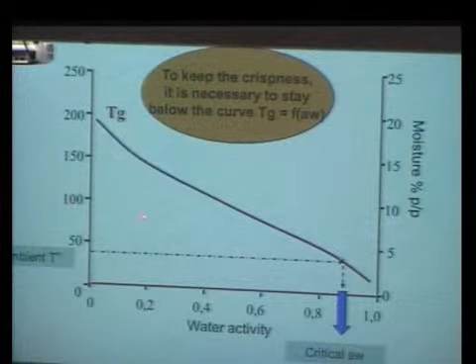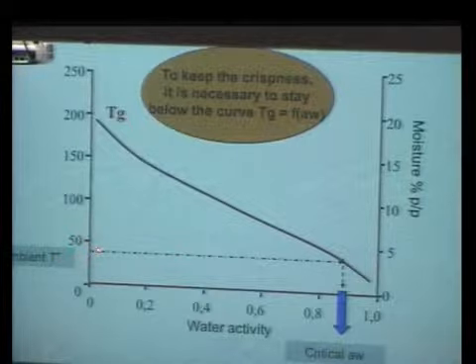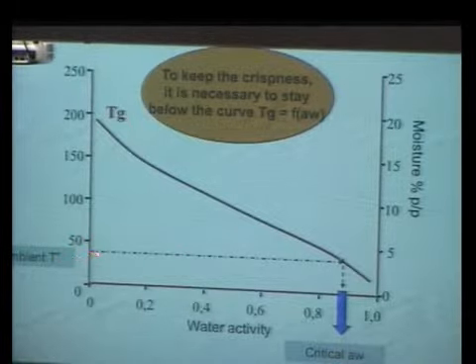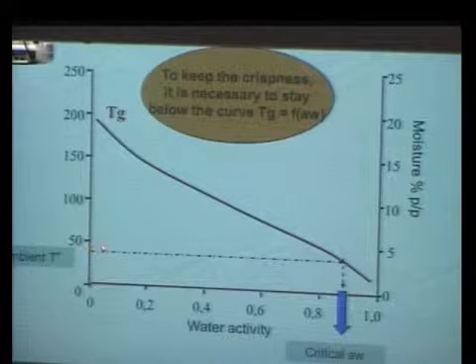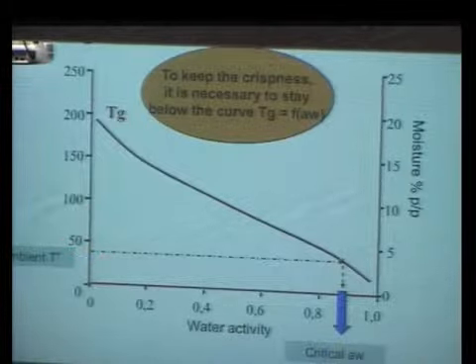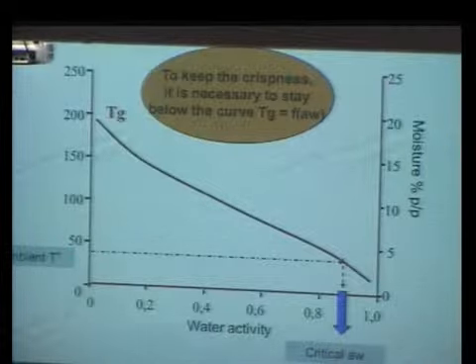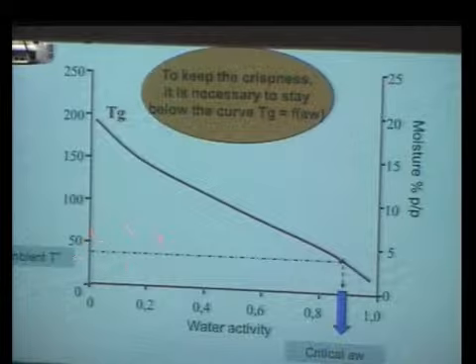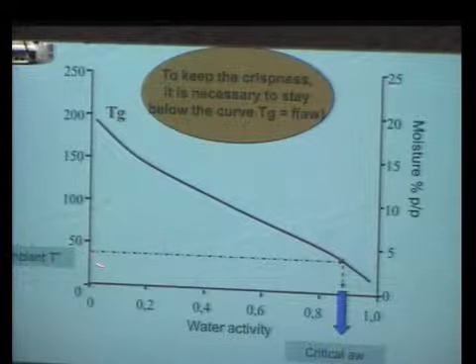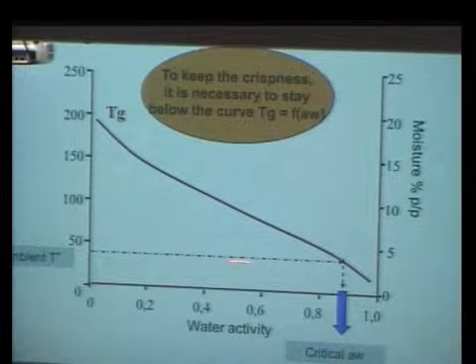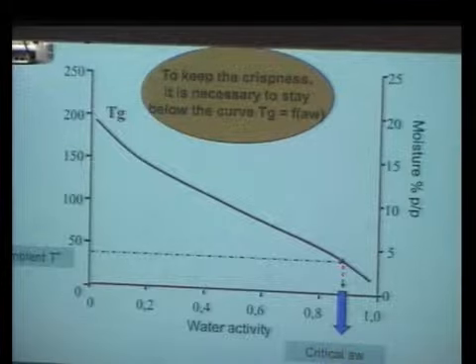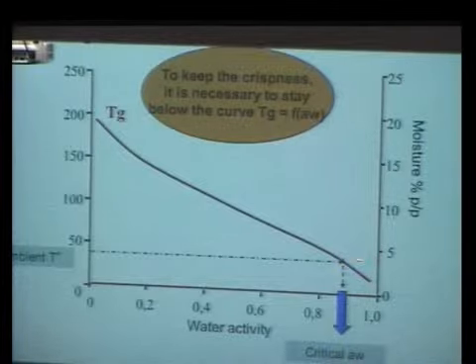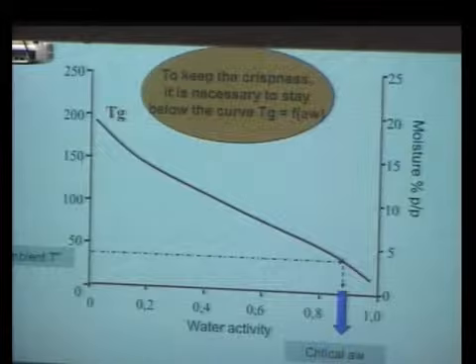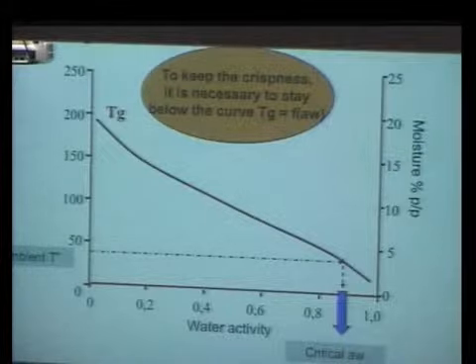is below this curve, okay? So when your product is stored at ambient temperature, as you can see, I took the ambient temperature near 50, okay, for my example. So when your biscuit is stored at ambient temperature, you can read here the critical water activities that should not be crossed. You should not cross the water activity because you will be above the temperature of glass transition. So your biscuit, poof, will be soft, okay?